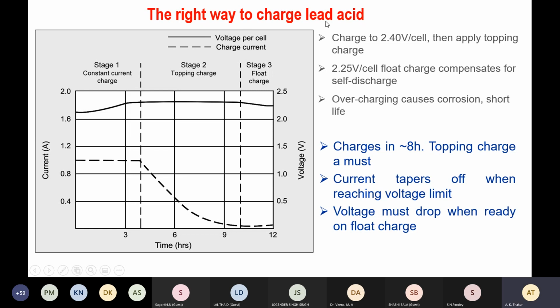The right way to charge a lead acid is, if it is designed for 2 volt, which it is, then it has to be charged to 2.4 volt per cell and slowly allow its voltage to fall down to 2.2 volt per cell under float charge condition, so that when the charger is removed, the voltage would stabilize at the rate of 2 volt per cell.